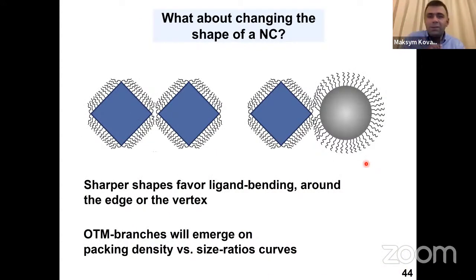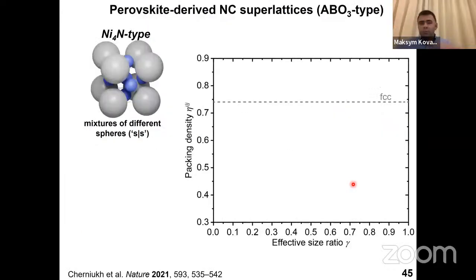Now, when you go to anisotropic shape, or actually it's isotropic, but a sharper shape, a cube, imagine a cube impinging on the sphere with the edge. And so this sharp contact will very likely lead to the bending of the ligands so that the cube and sphere can come closer to each other. By the way, this must happen also when two cubes approach each other through the edge or through the corner. And so this happens indeed. And this has a stabilizing effect so that you can have a lattice which is denser than without the ligands bending. And so that's a unique property of these sharper shapes, which allows us to observe new crystal structures.